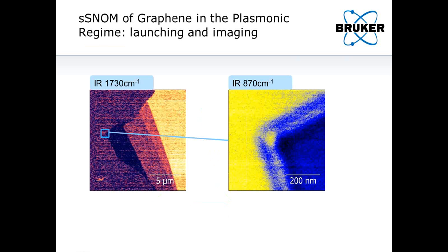So the type of image that you get if you zoom in on the corner of the single-layer graphene sample is shown here. This is an image at 870 wave numbers, and you see a clear feature that is related to the interference of the plasmon wave and the tip dipole.